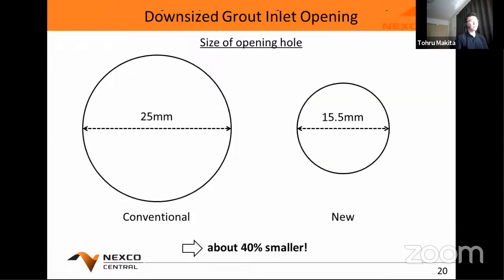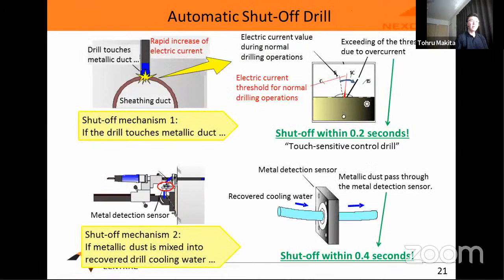So in the new method, the grout inlet opening was made smaller to decrease the section loss of concrete members and sheaths. In conventional methods, a 25 millimeter diameter hole was drilled for the grout inlet. But in the new method, hole size was reduced to 15.5 millimeters, and it is about 40% smaller than the conventional method. And to prevent damaging of steel rebars and tendons, an automatic shut-off drill is used in the new method.